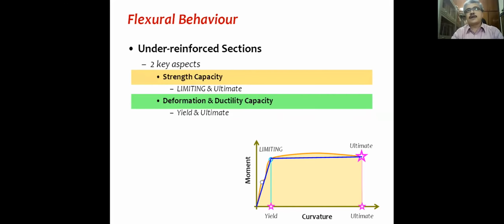One corresponds to where significant yielding is happening, and we design under-reinforced sections for the steel to yield. And then one corresponds to what we call the ultimate strength, which corresponds to crushing of concrete, or the secondary compression failure. And similarly for the deformations or curvatures, there is an effective yield curvature and an ultimate curvature. So now you see that the focus is shifting from strength alone to the entire load-deformation response, so that we look at both strength as well as deformation.